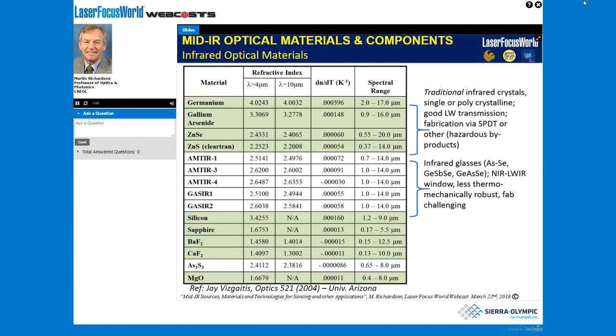We can rely on infrared glasses materials, non-oxide glasses like arsenic selenide and other materials that I've quoted here. Their great advantage is that they have an extremely wide window of transmission in the near IR, stretching out into the long wavelength IR, so beyond 10 microns. The disadvantages are that, being non-oxides, they are less stable thermomechanically. They usually have lower optical damage thresholds, and their fabrication in pristine form is also more challenging.